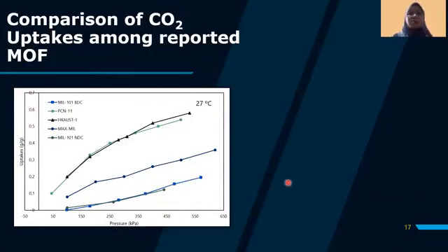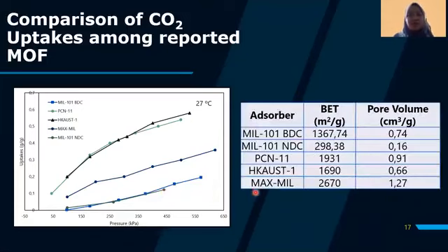So after that, we do the investigation of the CO2 adsorption. We do a comparison among other reported MOFs like MIL-101 BDC, PCN-11, and also MAX-MIL and HKUST-1. And here is our MOF, MIL-101 NDC. As you can see, the CO2 uptake of MIL-101 NDC is still less than the parent MIL-101 BDC. So that's why we need to optimize the synthesis reaction to get a better surface area and a better pore volume to get a higher CO2 capture.